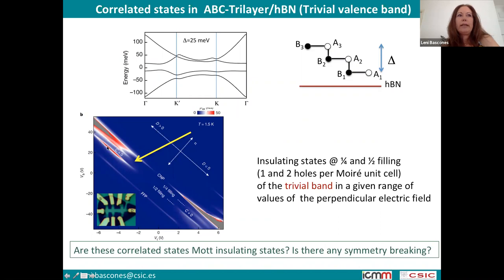In the case in which there is a trivial band, it was observed that there were two insulating states that appear when there was one hole or two holes per moiré unit cell. One hole is associated to having quarter filling, and two holes are associated to having half filling of the band. From the very beginning, there has been a discussion on whether these states are a Mott system.